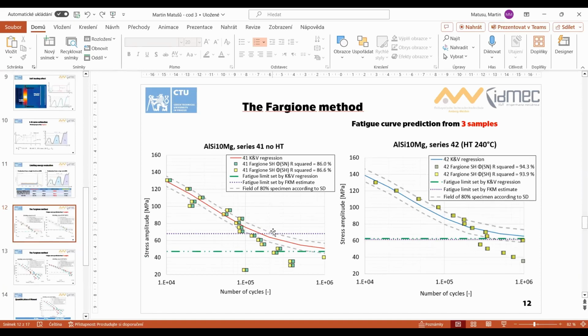Also, this is the K&V regression. We use 3 samples to predict the stabilized temperature and use the limiting energy as a parameter to estimate the number of cycles to failure. Here are both limiting energies, and you can see that there is a good correlation within the line, which is 80% according to the standard deviation field of 80%. And you can see that there is a good correlation between 10,000 cycles and 100,000 cycles, the slope of the Wöhler curve between the band, which is typical for aluminium.